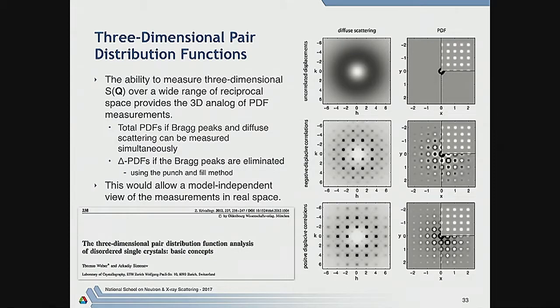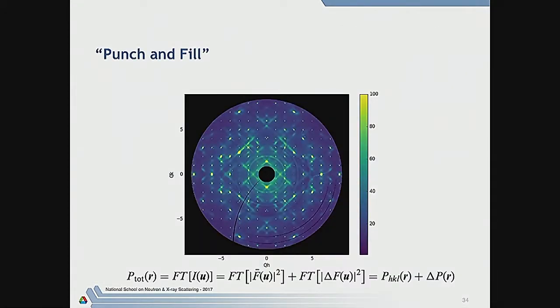And this is something that Thomas Weber and Arkady Simonov have been developing, and we've only been using in the last year. And it's called punch and fill. And the idea behind this is that if you do a Fourier transform of the scattering intensity, okay, so you're transforming stuff that's in HKL into real space again, you get what's called a Patterson function. So we haven't solved the phase problem when you do this transformation.